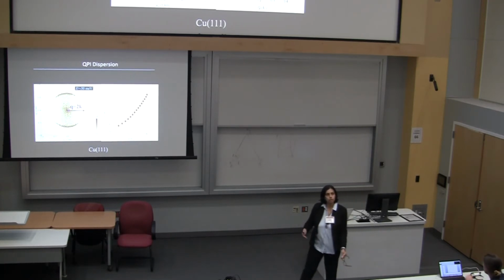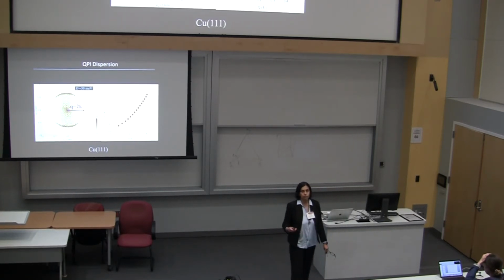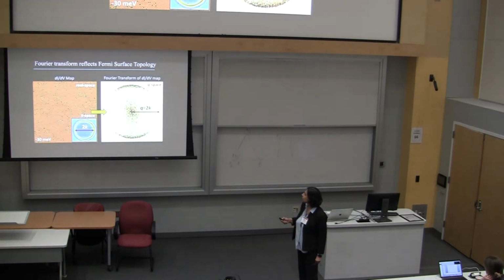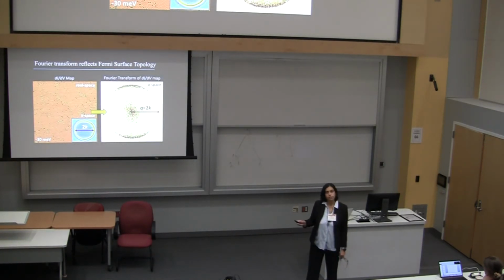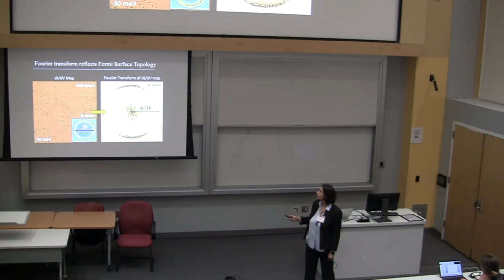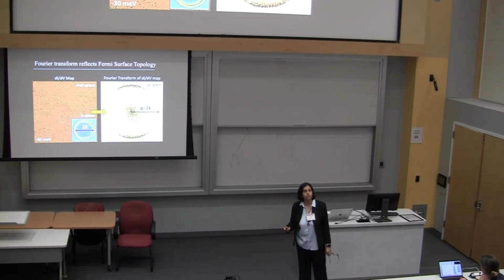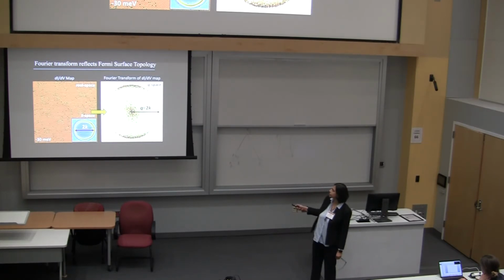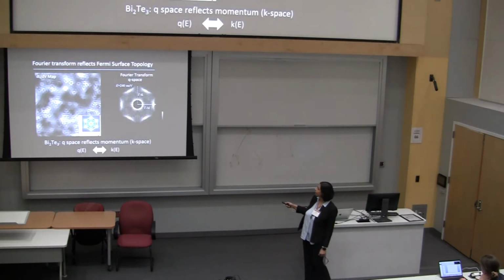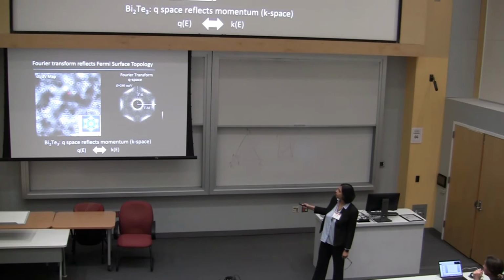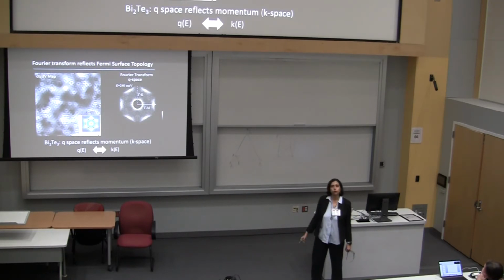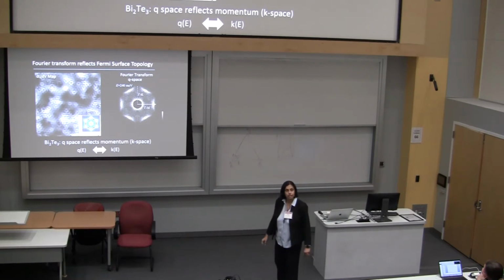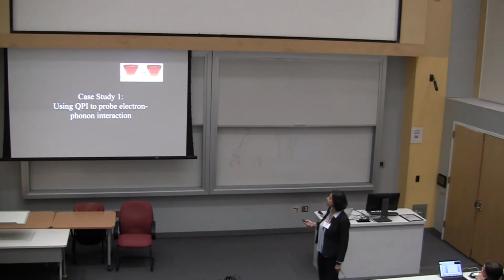Okay, so QPI is very, very powerful. You can get momentum space information. The other thing about quasi-particle interference is these Fourier transforms reflect the topology of the Fermi surface. So in this case, the Fermi surface was circular, so the Fourier transform looks circular. In bismuth telluride, for example, where the Fermi surface looks like a hexagon, our Fourier transforms also look like hexagons. So we can get really a huge amount of information using these techniques.